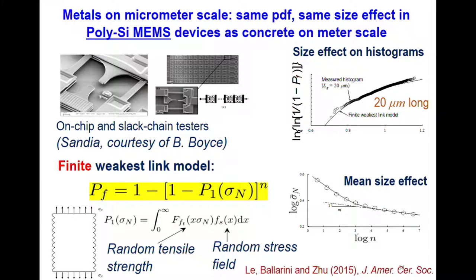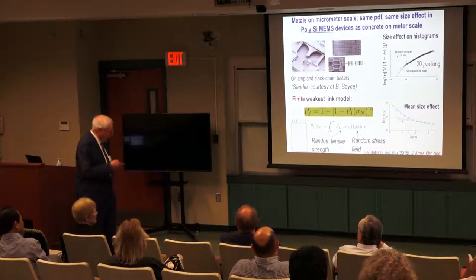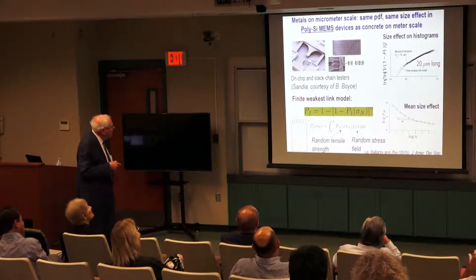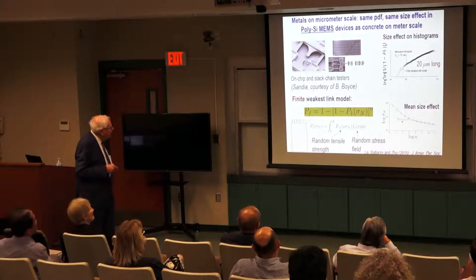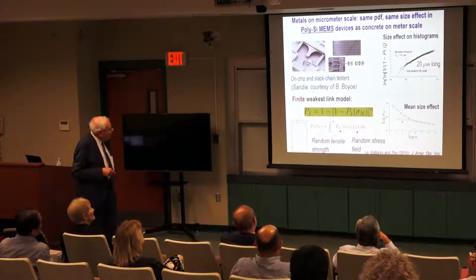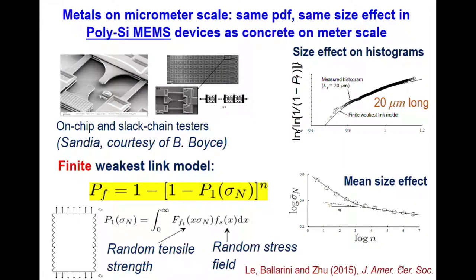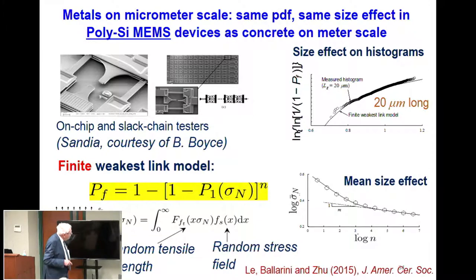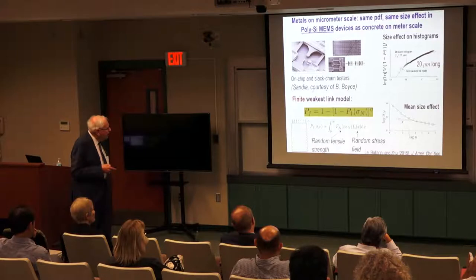My former student, Jia-Liang Le, who is in Minnesota teaching as an associate professor, tested at Sandia with Boyce similar problems for polysilicon on the MEMS scale. They use a slack-chain tester, which is generally used for testing many specimens on loading. You see again the same behavior. In Weibull scale, you don't get a straight line. You get a curve. That's verified here. And they tested size effect, and this size effect is shown here. It's not a straight line like with Weibull. It's a curve. So actually, in micrometer scale, every material is quite arbitrary.